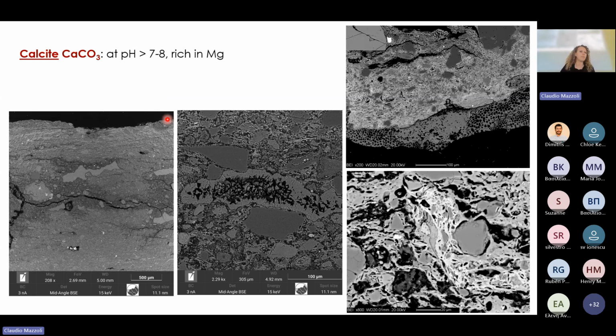And it can completely fill porosity like this large void, or it can form a geode-like structure, so partially filling the porosity. It can also permeate tiny pores that are in the size of nanometers or just a few micrometers. So the general effect that you can see is something like this, in which this whiter part, represented obviously by minerals having an average atomic number higher than the surrounding, is represented by secondary calcite filling the little porosity.